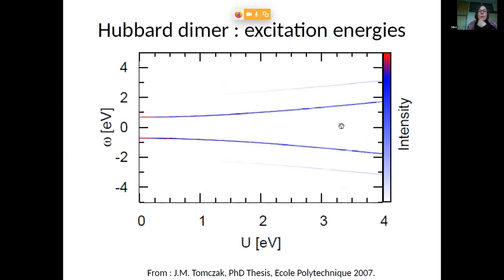Yes, okay. So you just take a Hubbard dimer as a function of U, and this is now the spectral function, a function of energy. And it evolves from bonding, anti-bonding, non-interacting, Hund-Mulliken, whatever you would like to call it, molecular level system here, to a system where you have four peaks. So here you have some faint, but still there, satellites, and the bonding, anti-bonding splitting is enhanced by U. So this is this square root of U squared plus T squared behavior, where the U enhances just the splitting that you observe. So now this is the exact solution of the dimer.